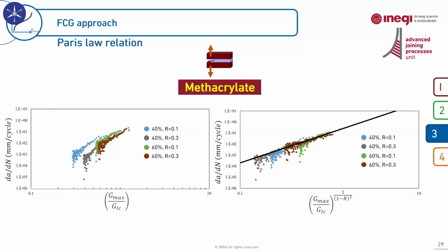I mentioned before that in fatigue crack growth characterization, we need to search for a good Paris law parameter to be able to construct a master Paris law curve. And here are the results. We actually did this test on a methacrylate adhesive. And by changing the Paris law parameter and by including the effect of R ratio, we were able to collapse all these curves into a single curve.